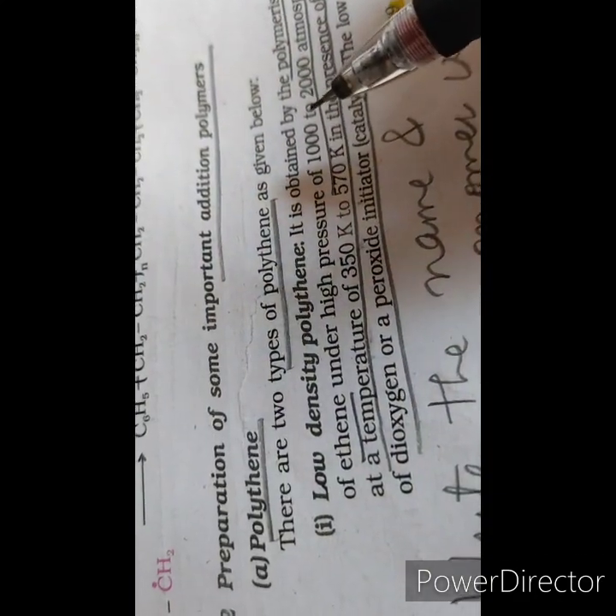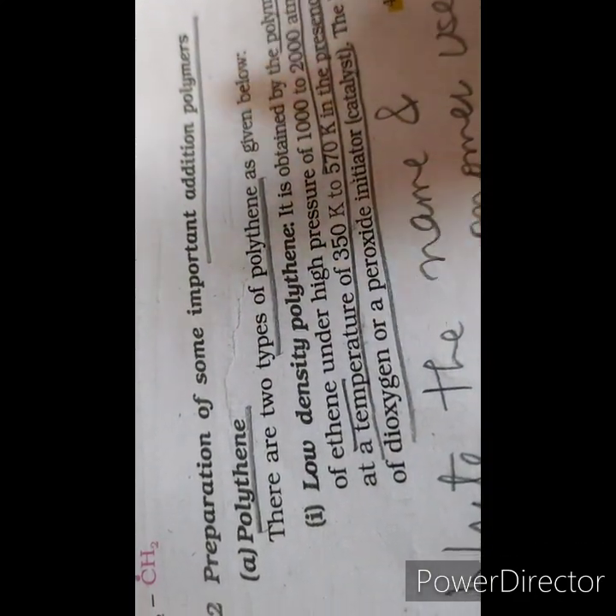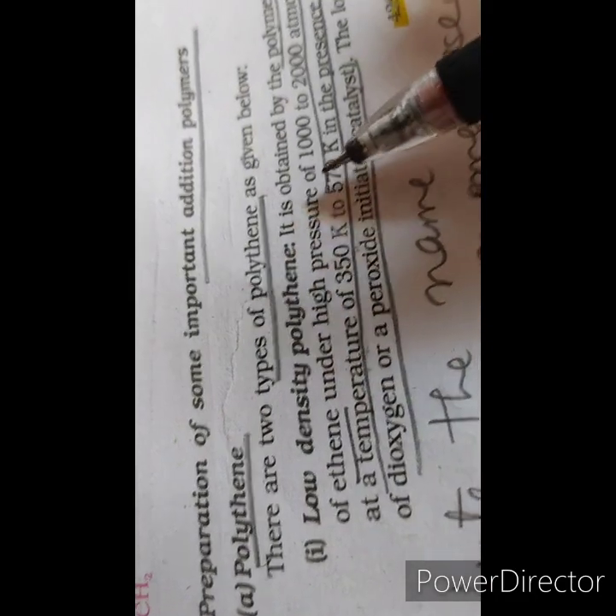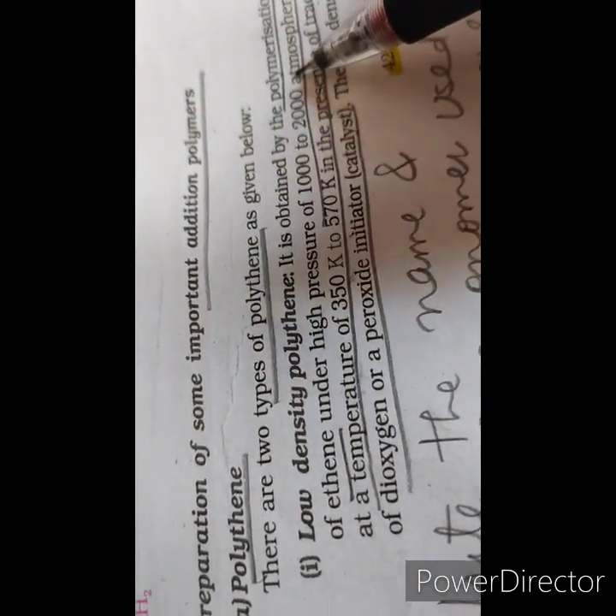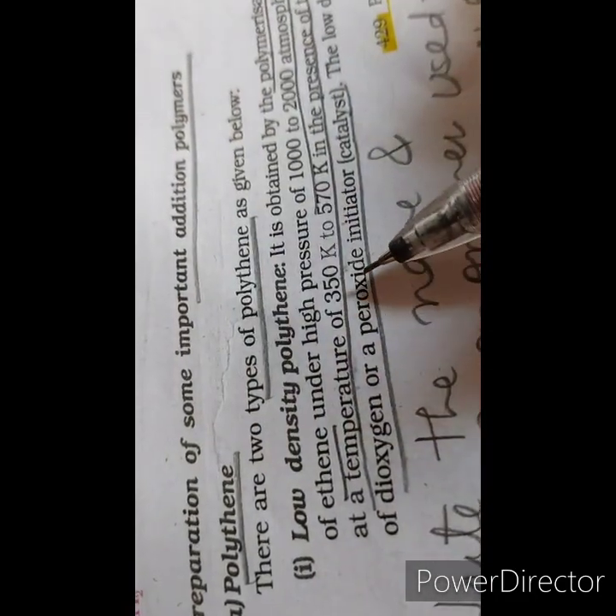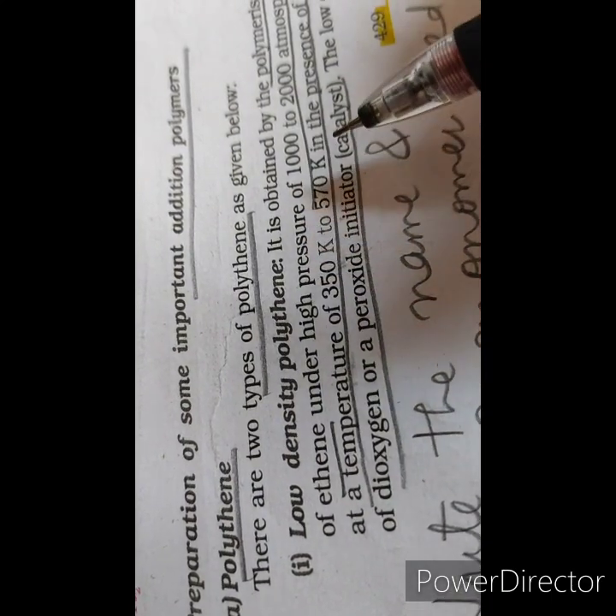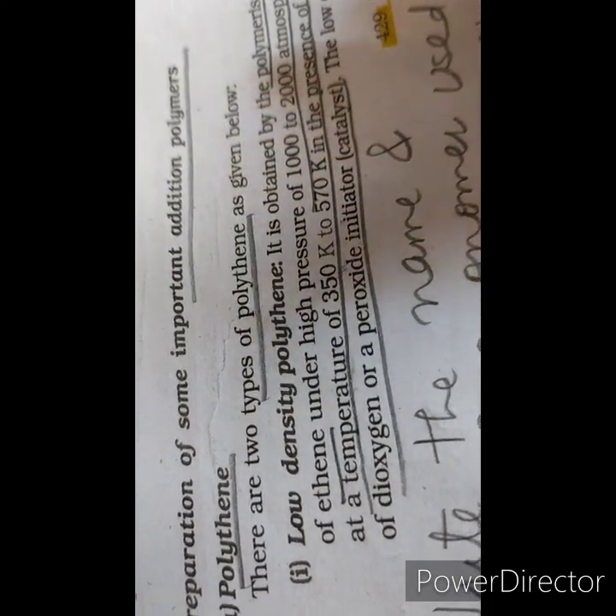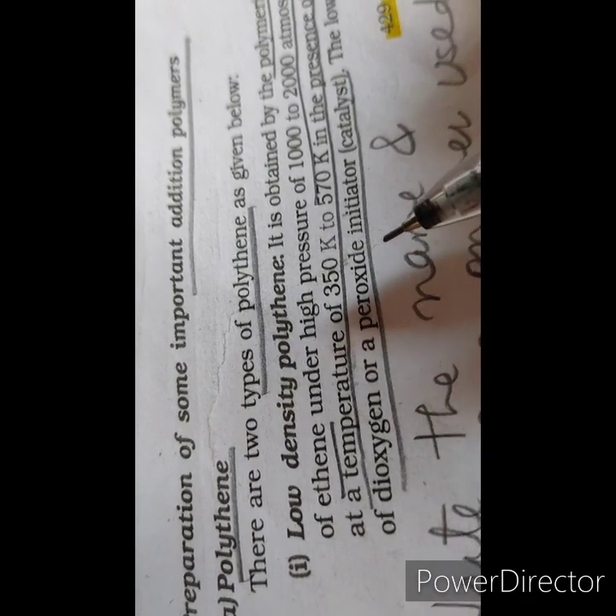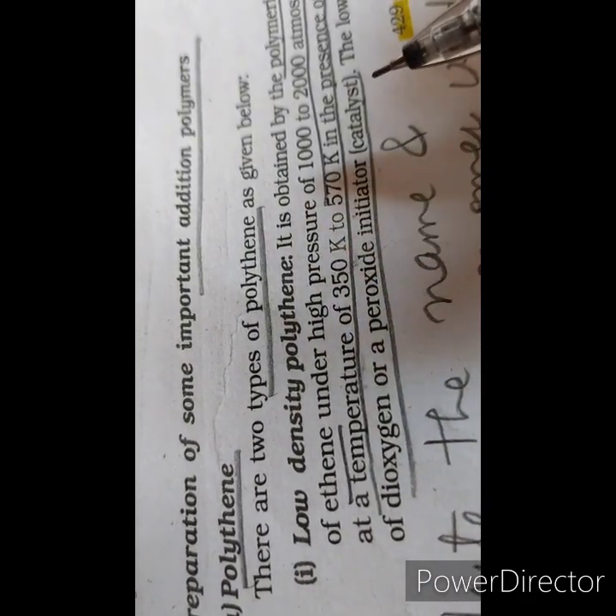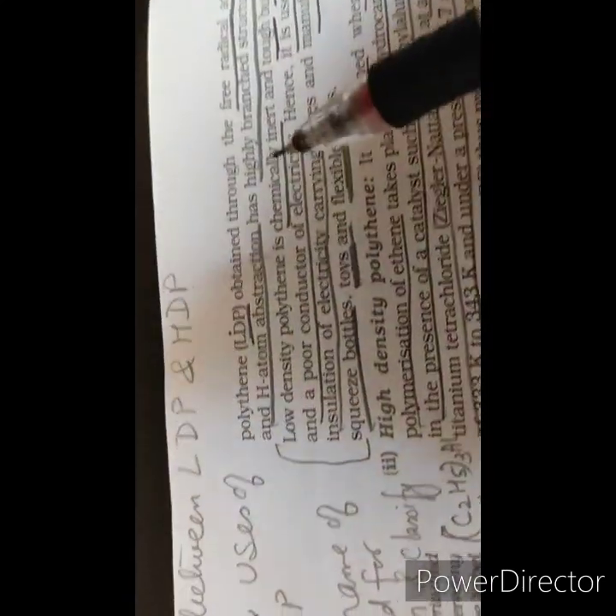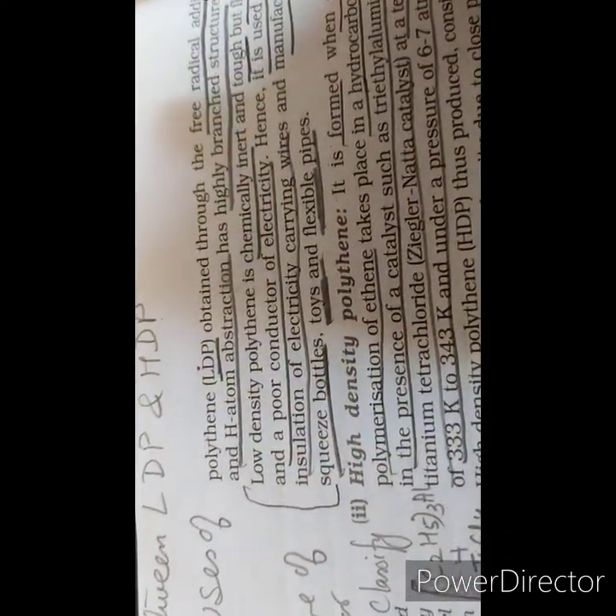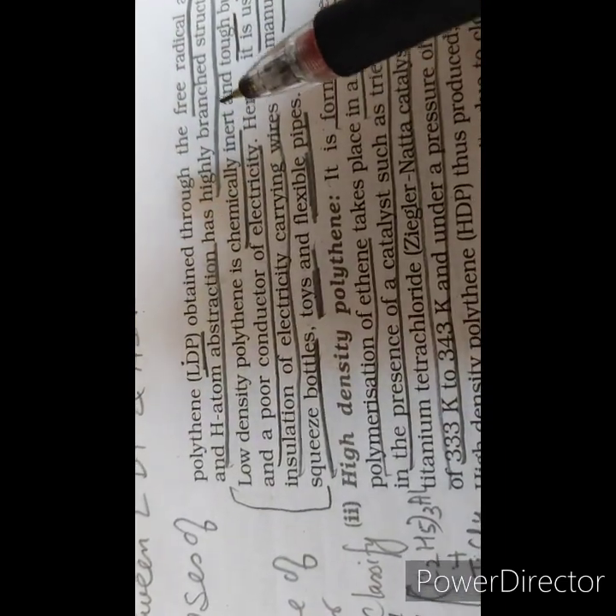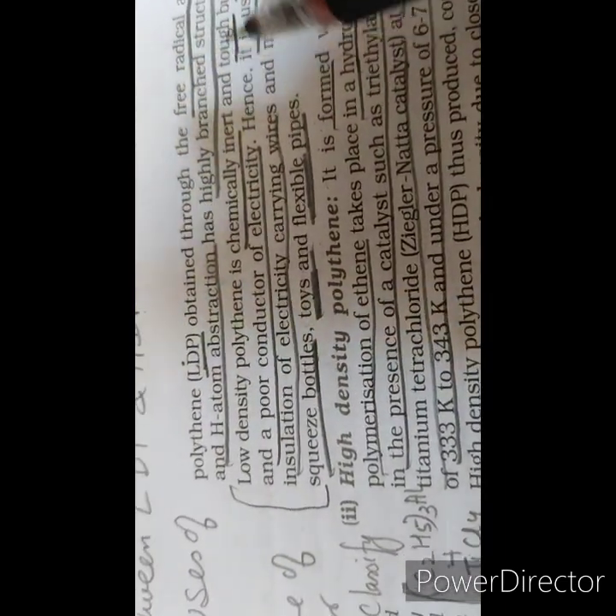This low density polythene is obtained by the polymerization of ethene under a high pressure of 1000 to 2000 atmosphere and temperature of 350 to 570 Kelvin in the presence of traces of dioxygen or a peroxide initiator catalyst. The low density polythene is obtained by free radical addition and it has a highly branched structure.